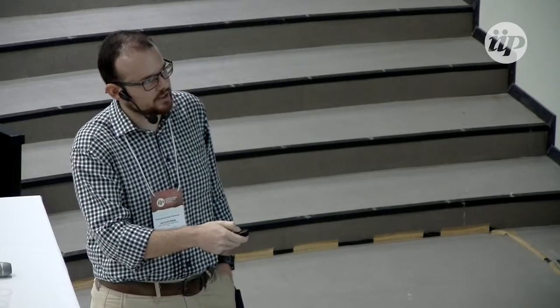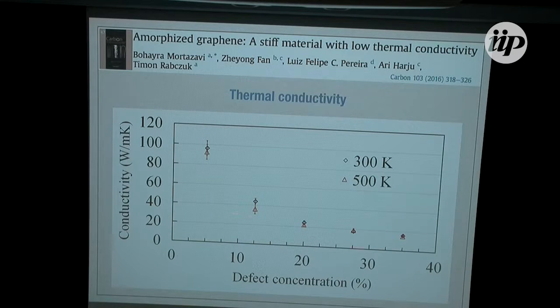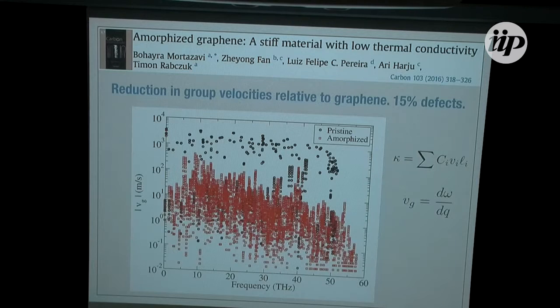We had to do equilibrium simulations, but we used the correct expression for the heat flux, and we calculate each component of the thermoconductivity from this integral of the heat flux autocorrelation function, which you have already seen today more than once. And when we do that as a function of the defect concentration, we see that the thermoconductivity decreases with the defect concentration, as expected. But it doesn't seem to depend much on temperature. So in this higher defect area here, 20%, 30%, almost 35%, the thermoconductivity is almost insensitive to temperature. And this is very characteristic of systems where the thermoconductivity is fully limited by defects.